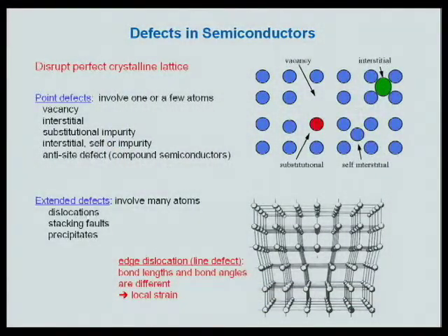And there are many impurities that can do this. But we also can have extended defects in a semiconductor. And an extended defect involves many, many lattice sites. This is an example of a dislocation where all of a sudden we have a plane of atoms that just stops. And so in this part of the crystal, we have perfect lattice. In this part of the crystal, we have a perfect lattice. But there's an extra plane of atoms stuck here. And right around the edge of this plane, the atoms are out of position. And there's a very large strain field. And so this extends into the board here, into the screen, for however long. And that's why it's called a line defect, because the disruption of the lattice is a long line that goes through the crystal. And there's a high local strain associated with that.